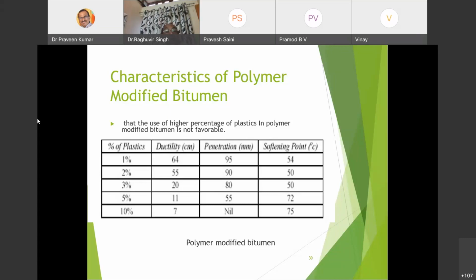For 1% plastic, the ductility is 64, penetration value 95, and softening point 54. At 2%, when plastic is increased, the ductility reduces to 55, penetration reduces to 90, and the softening point is 50. At 3%, ductility reduces to 20, penetration again reduces to 80, and softening point is 50.